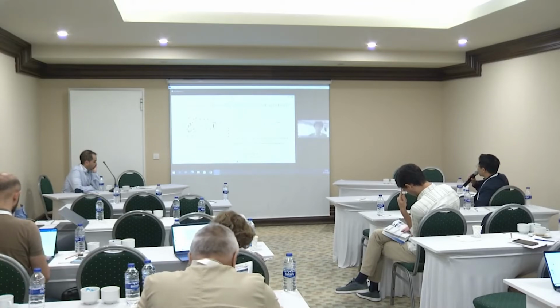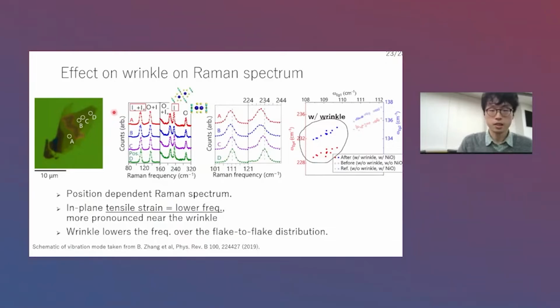Thank you for a very interesting talk. I have a couple of questions. When you mentioned that when you form the interface between nickel oxide and CGT, that enhances magnetism, right? And you attribute it to the tensile stress. So how does stress change the distance and also the bond angle, because that depends on the chromium distances. The angle means in-plane angle, right? Did you look into that? Does the DFT calculation support anything related?